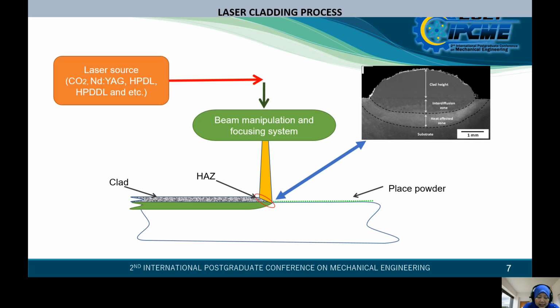Figure show laser cladding process. A very thin powder layer has to be melted for the substrate to achieve metallurgical bonding with minimal dilution. The cladding process starts with heat transfer of the liquid coating to the substrate. At this point, the coating begins to solidify. Energy from the partially solidified coating and the laser continues to partially melt the substrate and provide a metallurgical bond between the coating and surface. Then, resulting properties were characterized from surface topography, hardness, subsurface microstructure, and residual stress.